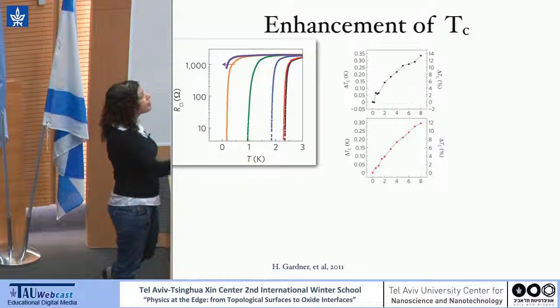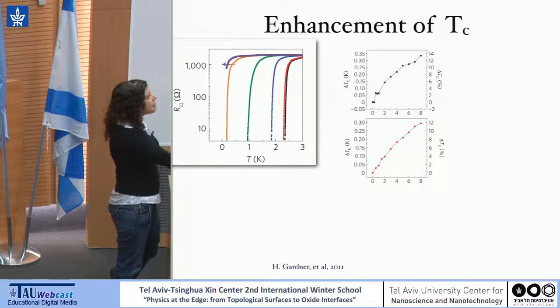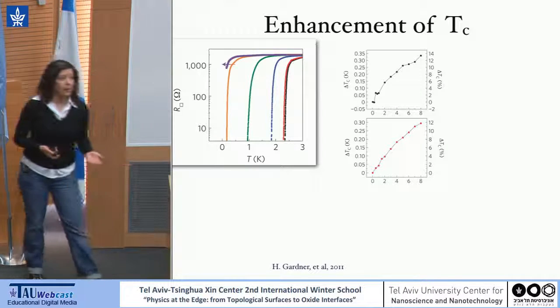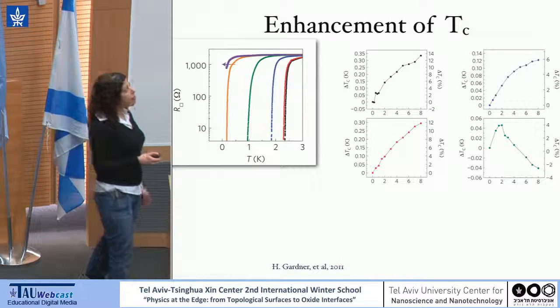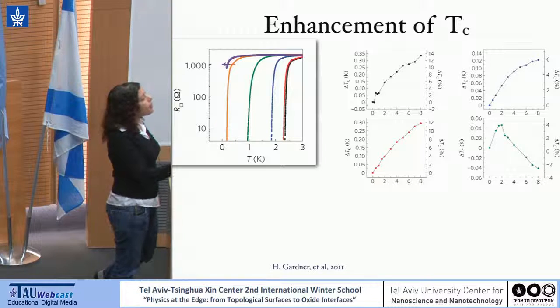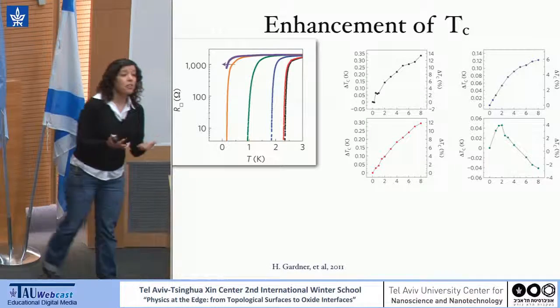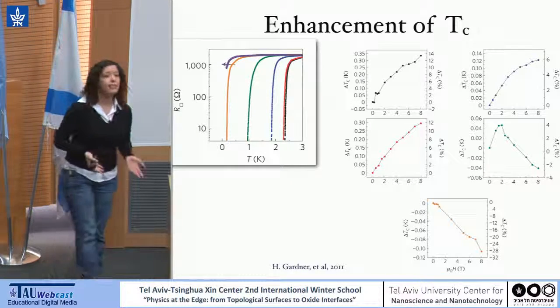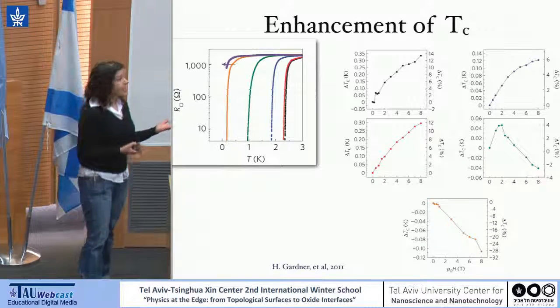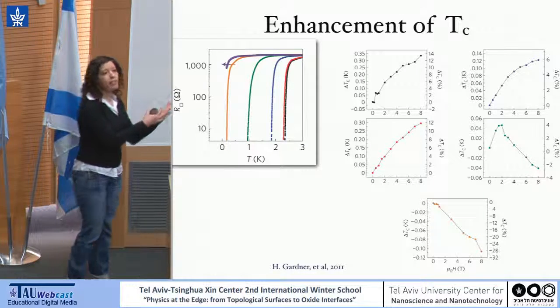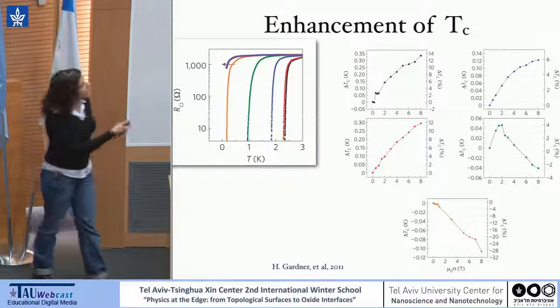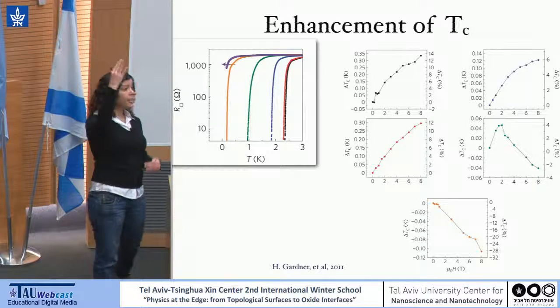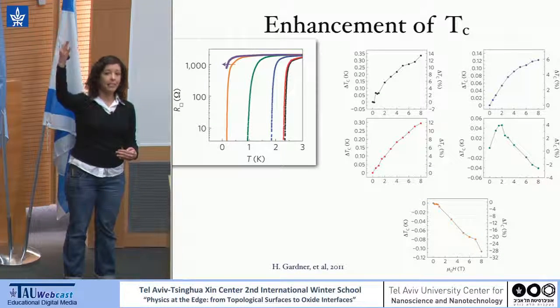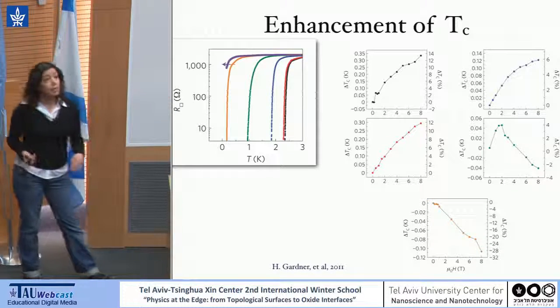The magnetic field grows. With a little bit of doping, TC goes a little bit lower, and also the change in TC goes lower. As they further increase the doping with magnetic impurities, they can see that the growth in TC goes down and eventually just disappears. And that tells us that actually that is not an effect of magnetic impurities, because just adding more magnetic impurities, we should see just a larger increase in delta TC. However, that's not really the effect.